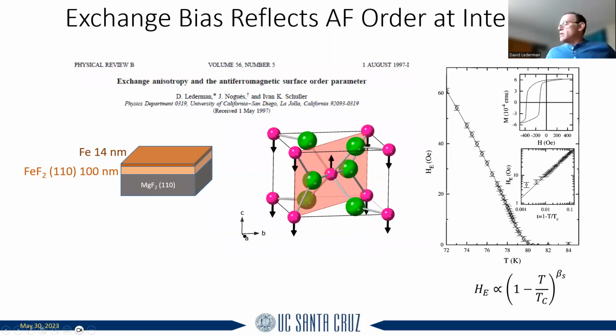Now, there's another thing I wanted to tell you about this, which is very interesting as well. This was a much earlier work, because I want to convince you that this is actually an interfacial effect. At the time I was still interested in phase transitions and so forth. And this is basically the exchange bias, the shift in this entire curve, as a function of temperature. We measured this shift very close to the phase transition temperature, and I was able to fit this to a rounded power law.